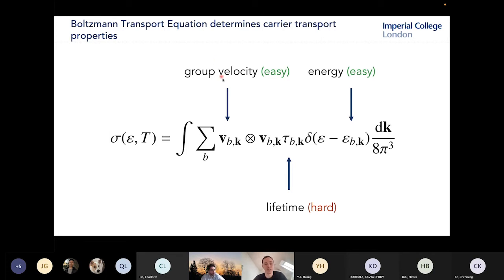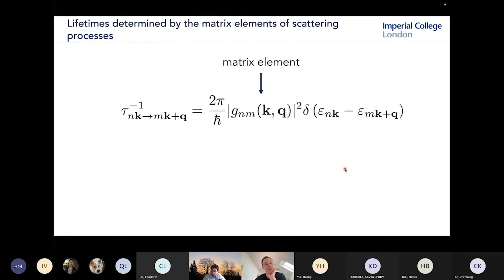Now, the group velocity and the energy are very easy to obtain. We get them for free just from a density functional theory calculation, which is just a standard calculation in our toolbox. But the lifetime is very difficult, and it's really where almost all of this complexity lies in obtaining transport properties. So the way we obtain these lifetimes is through Fermi's golden rule.